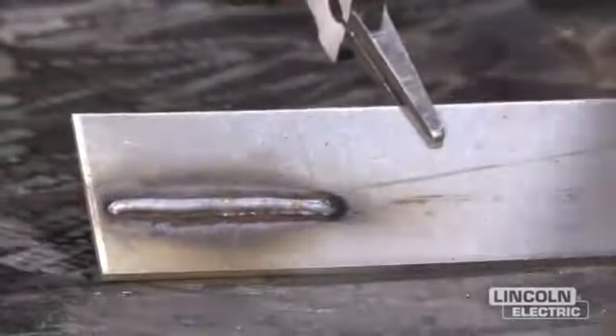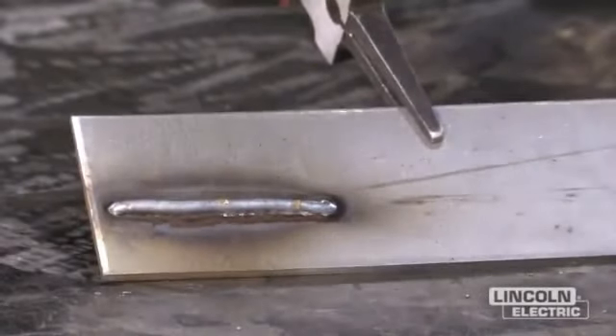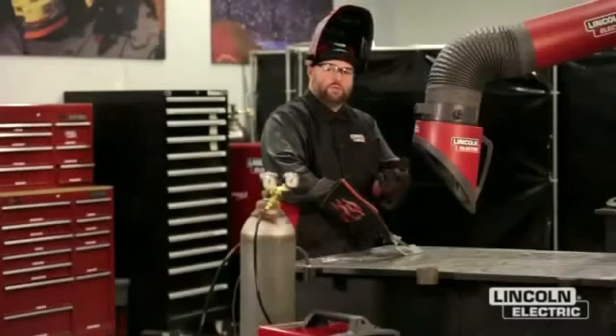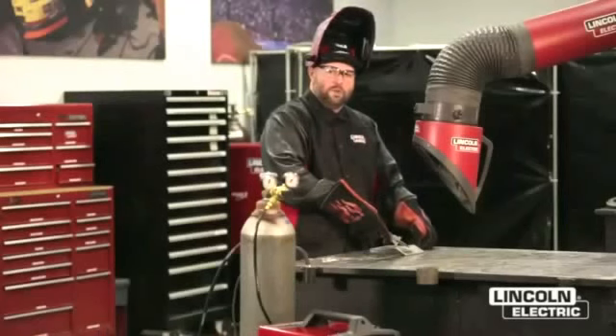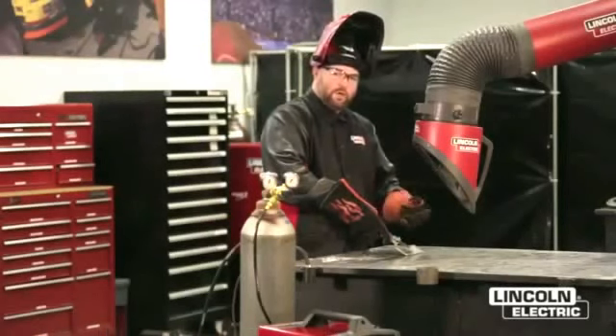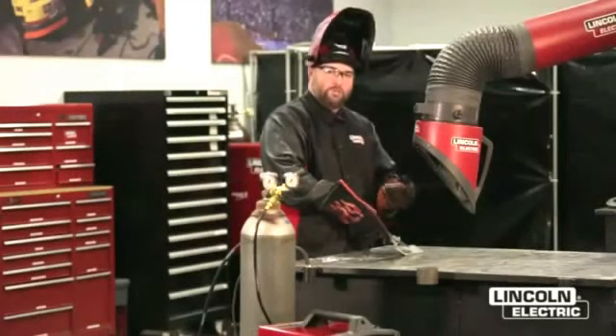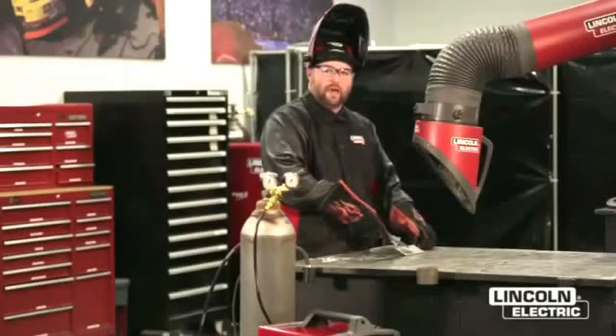So what you'll notice here is you could tell in the arc the wire was wanting to stub. We had too much wire for the amount of voltage that we had set. So again, to overcome that, we can either take our voltage up or bring our wire feed speed down.